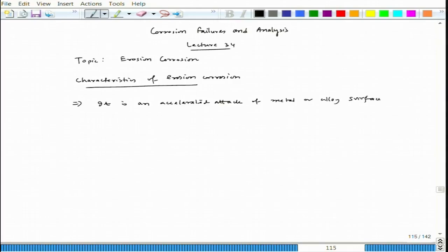In fact, in that regard, as I mentioned, if we do a stagnant test, let us say on 316 SS, this is the steel, in a stagnant condition, and the medium is, let us say, the slurry which contains FeSO4 plus H2SO4, this is the strong acid. In that case, at 60 degree Celsius temperature, even the attack would be very small on that 316 metal surface.